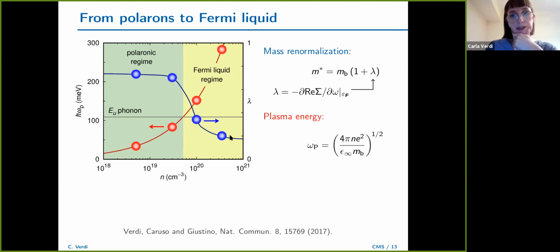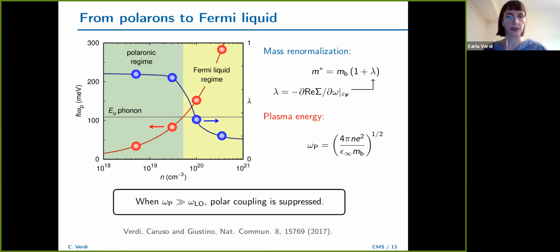We can rationalize this behavior if we look at the plasma energy of the system. Here I'm talking about the plasma formed by these added carriers in the conduction band bottom. You see this transition between a polaronic regime, where you have a large-ish mass renormalization, to a regime where the electronic quasiparticles are weakly interacting. This transition happens when the plasma energy becomes larger than the characteristic longitudinal optical phonon energy of the system. What this is telling us is that when the plasma energy is large enough, or correspondingly when the density of electrons is large enough, then the polar coupling is suppressed. This is very interesting, and it suggests a way to engineer the electron-phonon coupling when the longitudinal optical coupling is the dominant one.